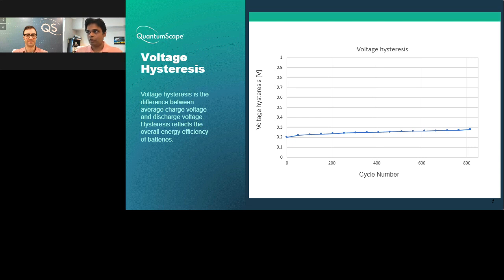And so the way in which one can infer coulombic efficiency of lithium metal cells especially is to look at how much lithium foil they had. And there's actually a very nice analysis that we put out in a paper in the Proceedings of the National Academy of Sciences last year that shows the trade-off and the thickness. Once you know the thickness of the lithium foil that is being used and the cycle life that they are getting, then you can use that to back calculate what the coulombic efficiency that those cells have. And I think it's now quite clear that the liquid cells are about 99, but well below the 99.99 numbers that was shown here. And so as a result, they have to make the compromise. All lithium metal cells that use liquid electrolytes have to make the compromise of using a lithium foil.